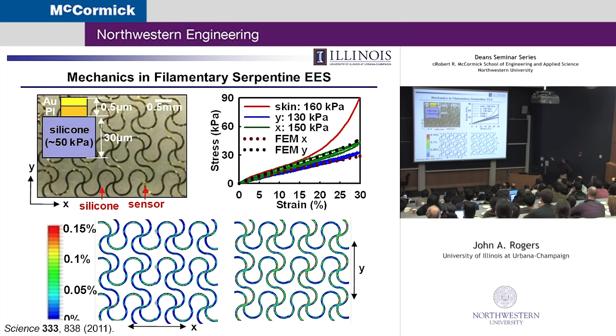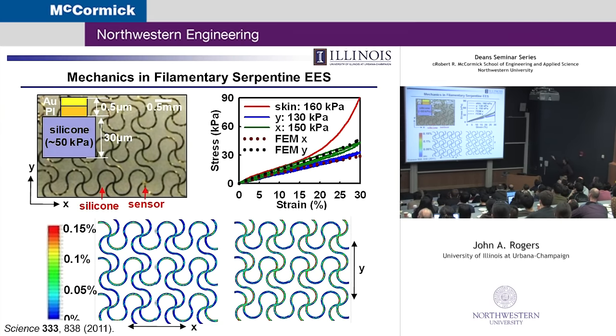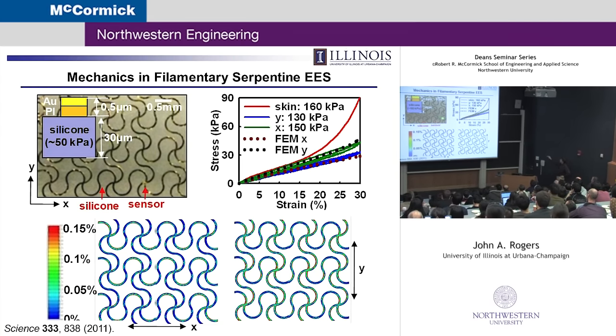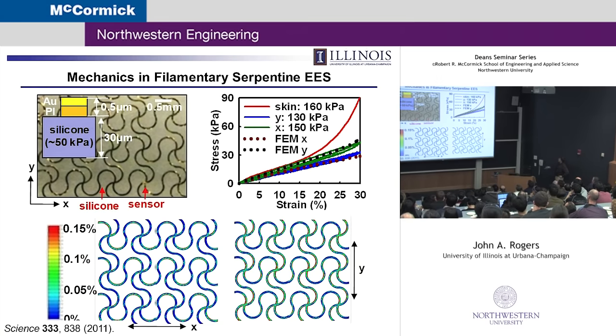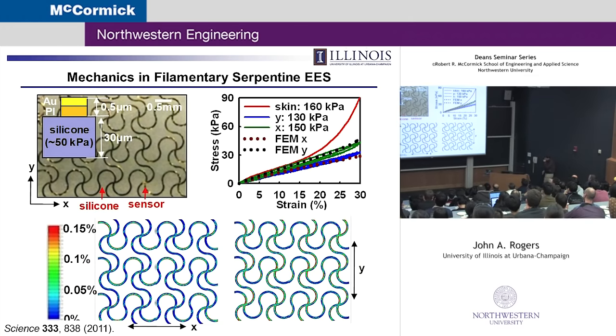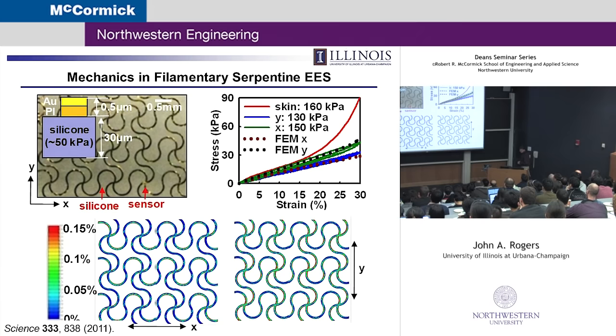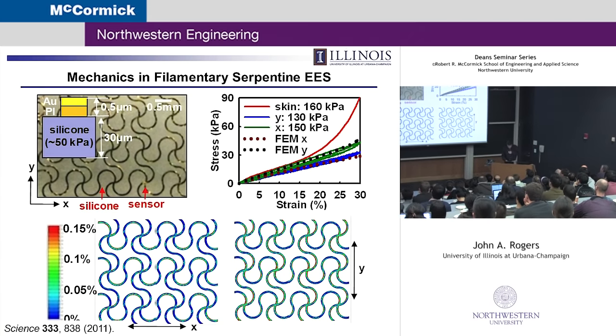Here's what the circuits look like. Again, if you've done this carefully, you can match this slope over the entire strain range of relevance up to about 20%. So the effective modulus, a little bit different in X and Y, is right in the range of skin and very well aligned with the design tools that we're using to lay out the mechanics. So that's how you do it.